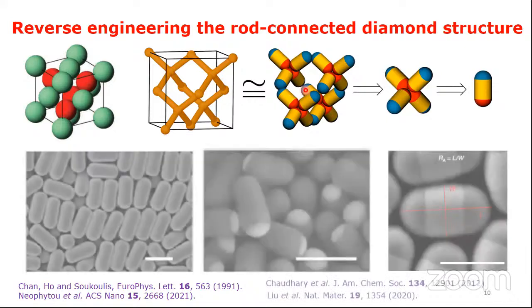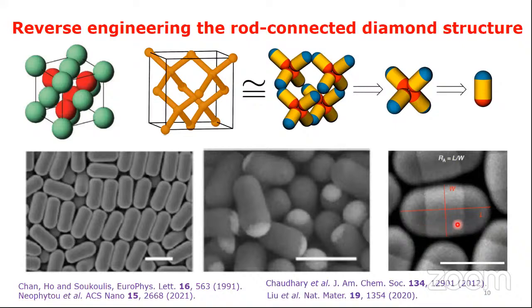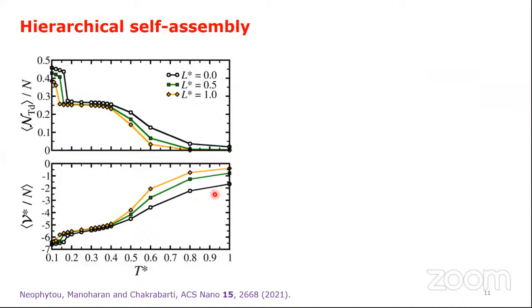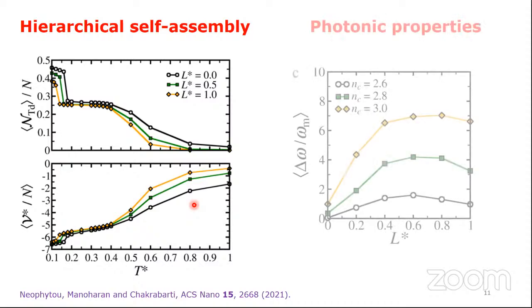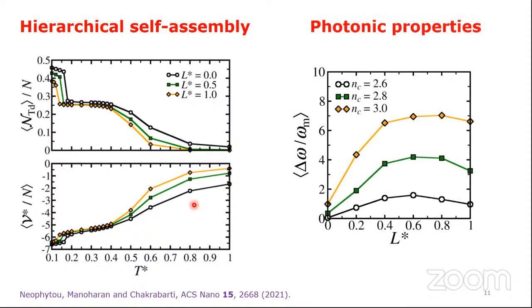Such tri-block patchy particles are now indeed synthetically available, as shown here. To cut a long story short, the two-stage self-assembly does work here, as summarized on this slide. The important point to note is that it works for a range of aspect ratios. In the limit of L star equal to 0, we have a tetrastack crystal. However, the self-assembly yields a mixed phase of both cubic and hexagonal components. For the segmented rod-connected diamond structure, we find that both the cubic and the hexagonal polymorphs support a complete photonic band gap, and the band gaps spectrally overlap.